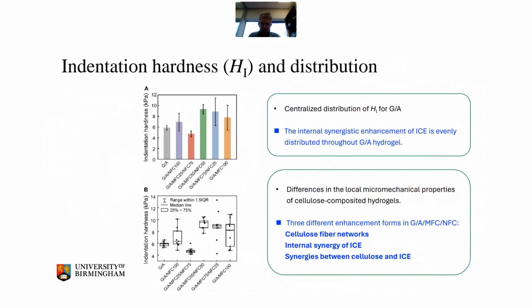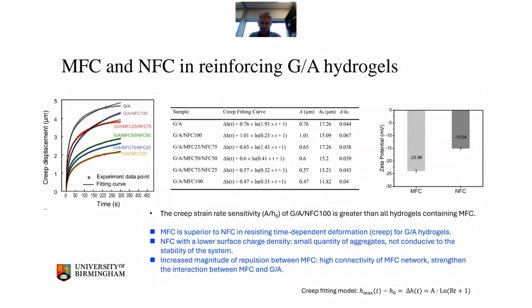Also, before I talk about that, he's talking about different enhancements coming from the cellulose fibers themselves, from synergy between the cellulose fibers and the ionic covalent entanglement networks, and also between the two things. Hardness is a slightly less useful parameter than modulus for these things, but more information is again found through looking at the time-dependent deformation. So we're applying a similar model here, and what we're seeing, if you look at the left, is that